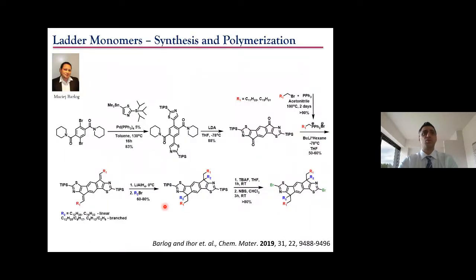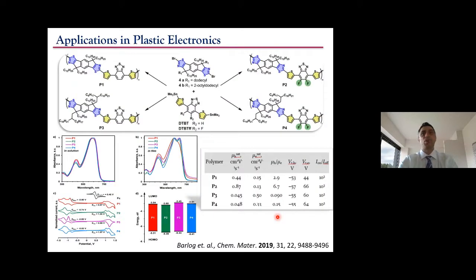So the postdoc that was working in the group, Maciej Barlog, the idea was to implement these thiazoles, as I said, the nature-derived or thiazole-based electron-deficient system, on these ladder-type systems. I'm not going to talk about the synthesis, I'm going to keep it basic, but we managed to make some different materials having different alkyl chains to give us the solubility for these materials. We made some polymers, and as you can see from the table over here, the highest mobility we obtained was 0.87. I should just highlight this. This is probably one of the highest mobilities reported to date with these types of thiazole materials. Usually the values go between 0.2 to 0.5, but 0.87 is one of the highest reported to date.